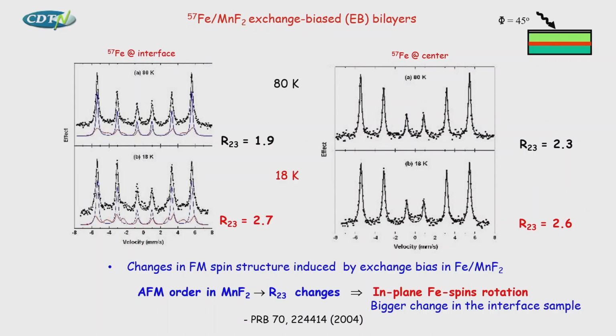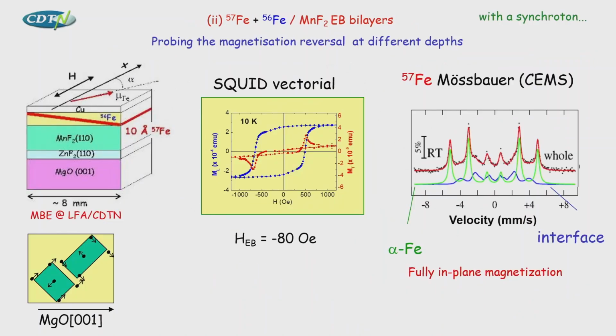But we wanted to see what happens really during the magnetization reversal. And then we got the beam time at the synchrotron in Grenoble, in the ID18. And then we prepared a sample in Belo Horizonte, a sample with a wedge of iron 57, this is iron 56, and then with 1 nanometer of iron 57 like this, okay? And we see also that this sample has exchange bias, was very well characterized. We see that the interface is sharp. We see here, let's say, the integral CEMS spectrum.